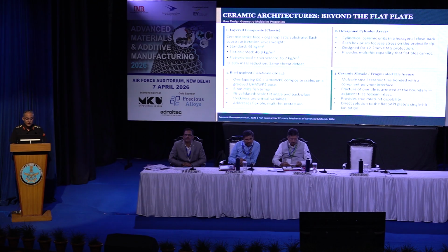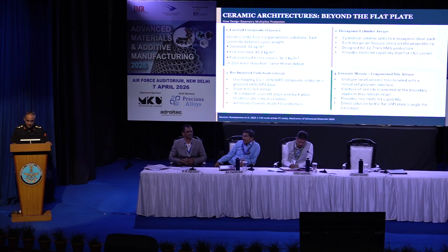And the fourth one is ceramic mosaic. The fourth architecture directly answers the question every commander asks: what happens on the second hit? And that is very important to know, that a monolithic plate is one structural unit. One round creates a fractured cone that compromises the surrounding area. The second hit in that zone meets a partially defeated material. A mosaic array breaks that propagation chain. Each tile is bonded through a compliant polymer interface. When one tile fractures, the adjacent tile does not know it happened.